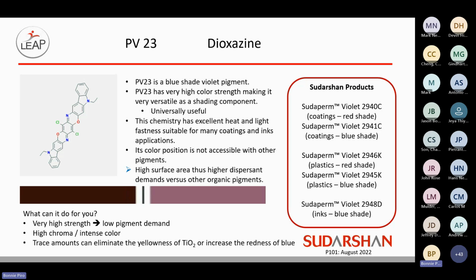That has a very useful position for that one. Its color position by itself is not accessible with other pigments. And one thing to note when you're formulating with this, especially in the liquid coating area, is it does have high surface area. So the dispersion demand is going to be higher than other organic pigments. What it can do for you, because of that very high strength, you can get away with a lower pigment demand to get what you need out of it.